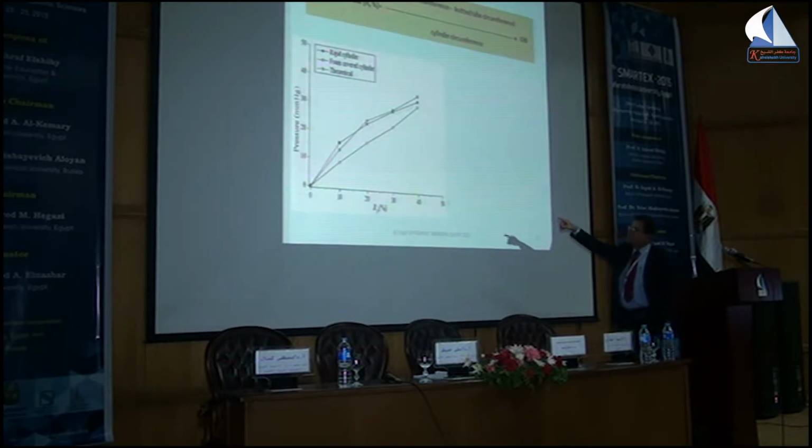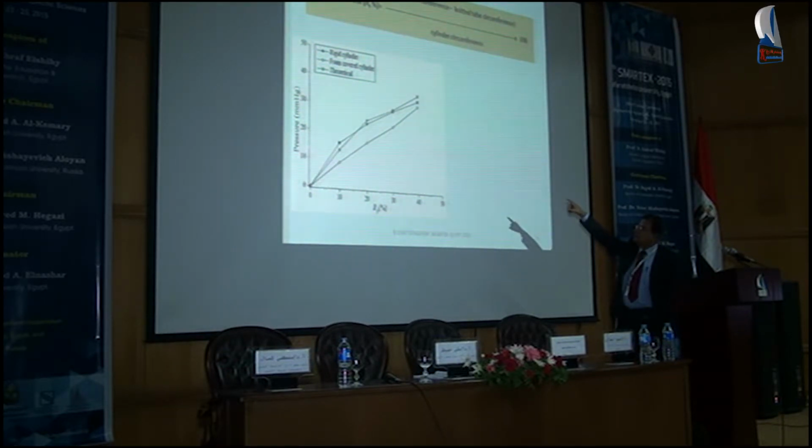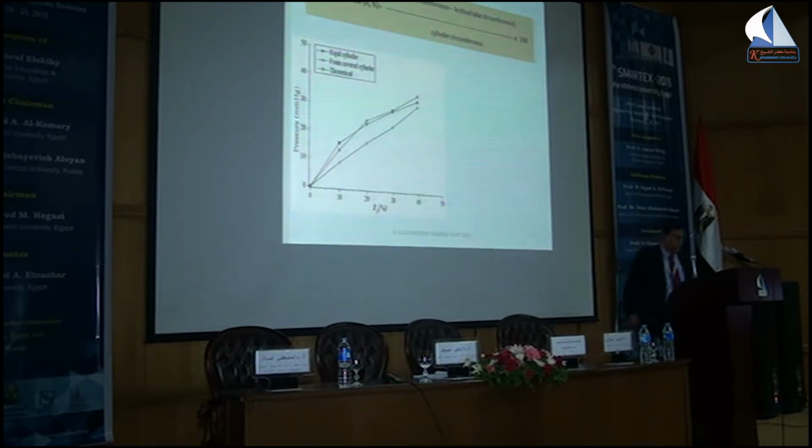Whereas where the rigid cylinder was covered by a foam which is compressible, we see a tremendous departure from the one where only the rigid cylinder was used. It basically means that the Laplace law is not estimating pressure correctly when the surface of the cylinder is compressible and not really rigid. In the case of the rigid cylinder, there is a perfect match.